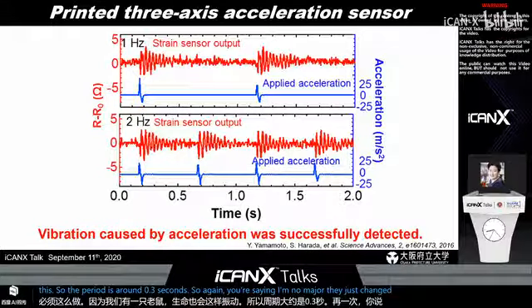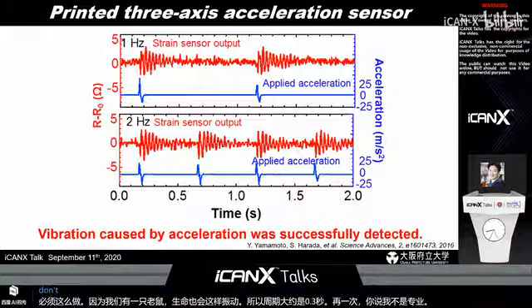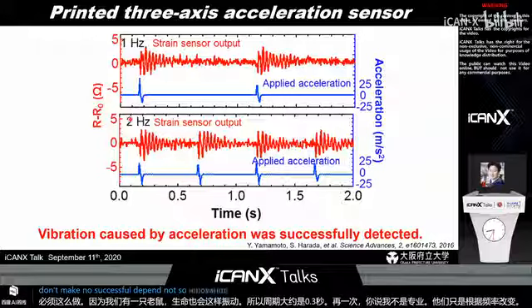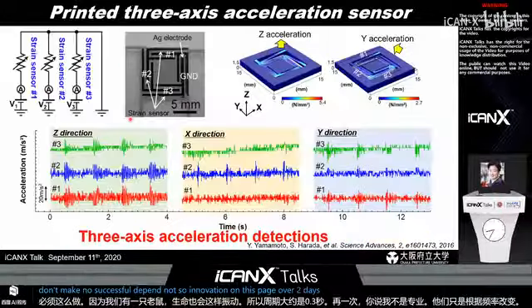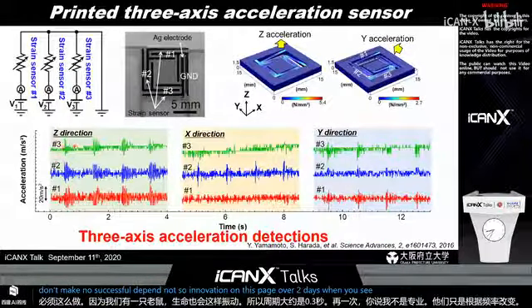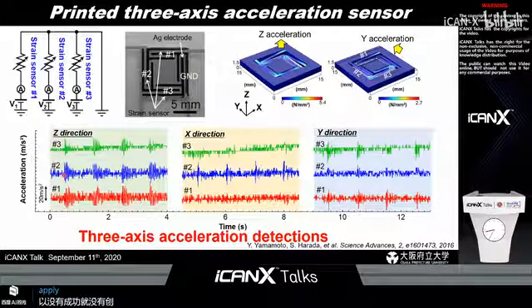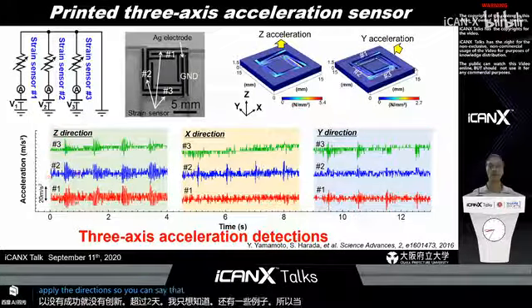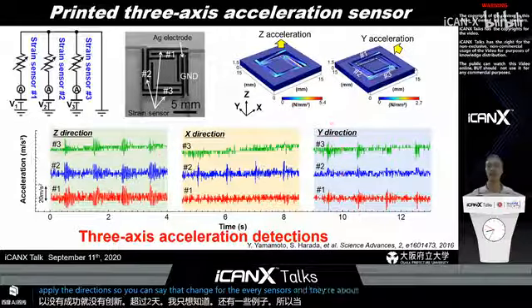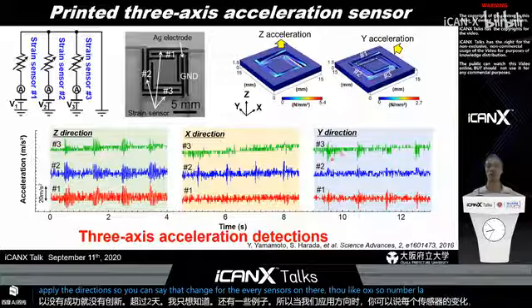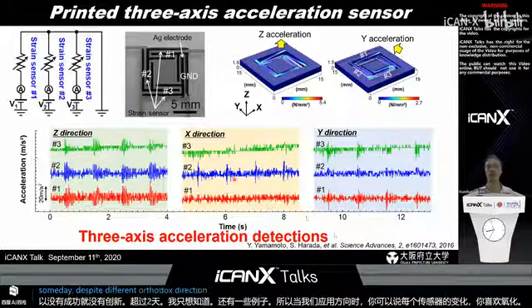And also depending on the frequency, we can successfully monitor the different accelerations and the speed of the accelerations. And then this is the simultaneous monitoring of the 3 strain sensors. When we apply the direction, we can see the strain change for every sensor. At the y-axis, number 1 and number 3 show some spike difference. At the x direction, number 2 shows only the resistance change.